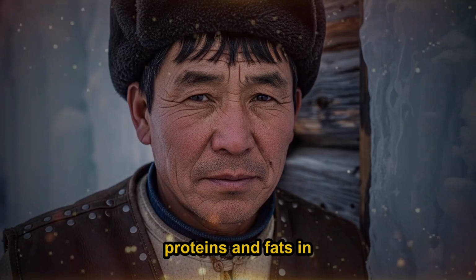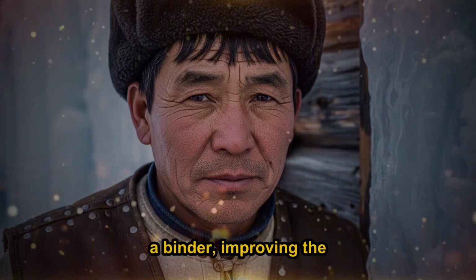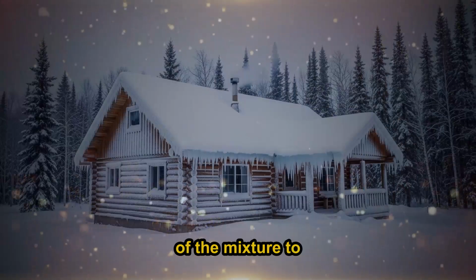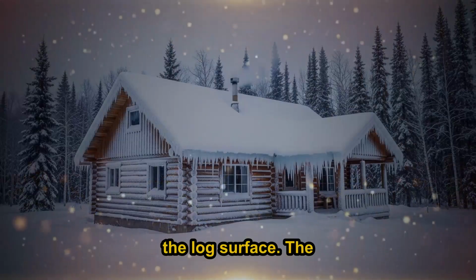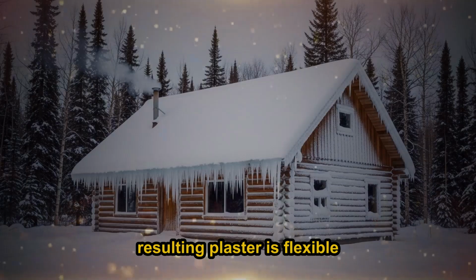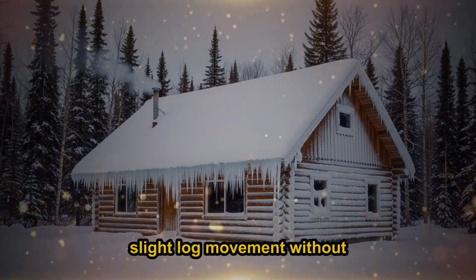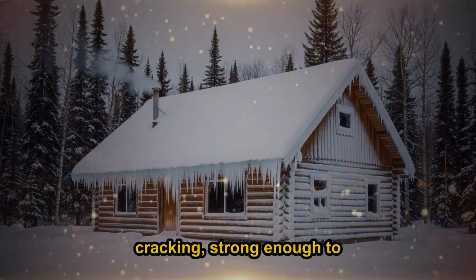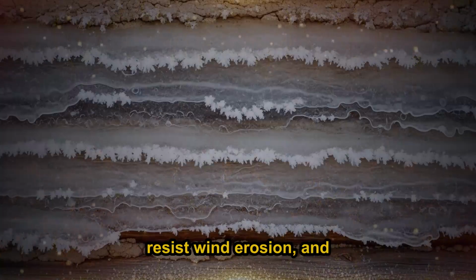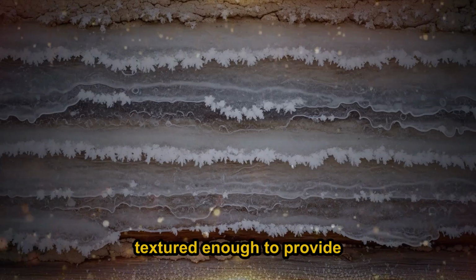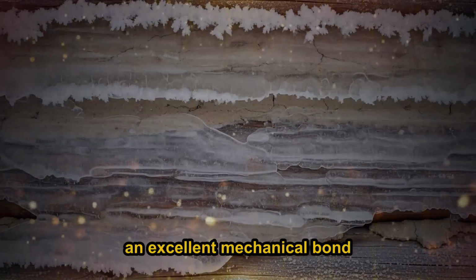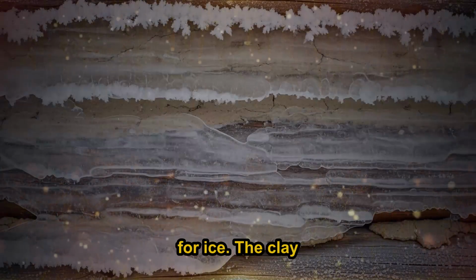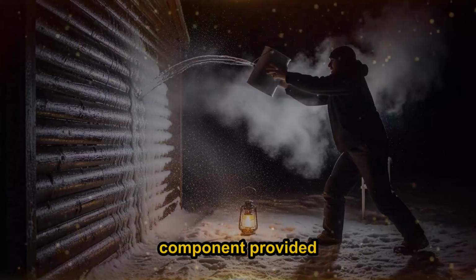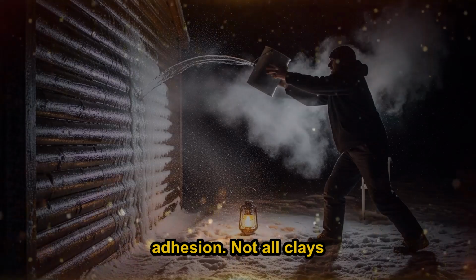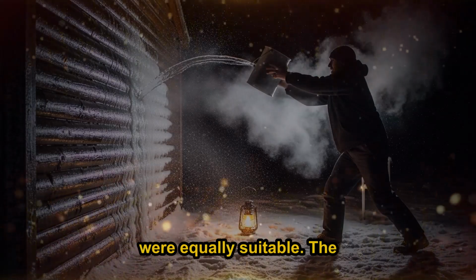The proteins and fats in the dung act as a binder, improving the adhesion of the mixture to the log surface. The resulting plaster is flexible enough to accommodate slight log movement without cracking, strong enough to resist wind erosion, and rough-textured enough to provide an excellent mechanical bond for ice. The clay component provided the bulk and the adhesion. Not all clays were equally suitable.